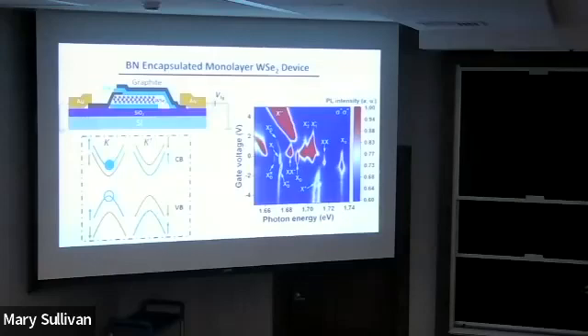The energy in this case is slightly tricky, but the binding energy is given by the PL resonance of this one and this one. So you can see this emission is roughly 20 milli eV below the exciton. This one is 30 milli eV below the exciton. And this has been done by many, many calculations showing that's the case.